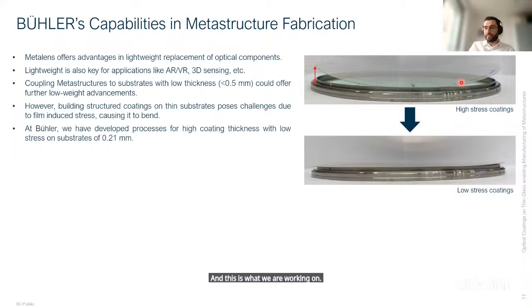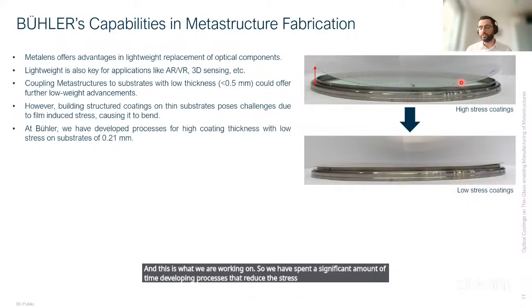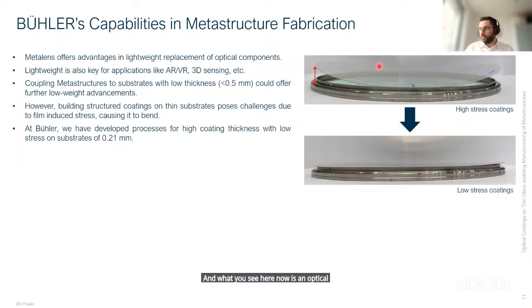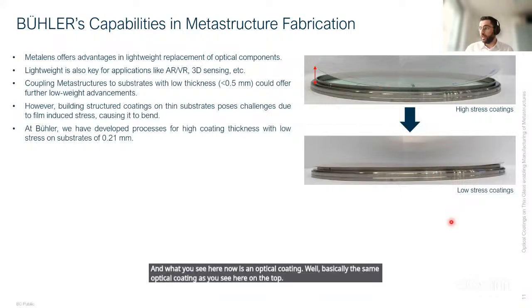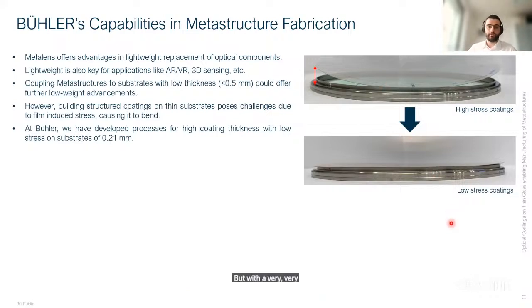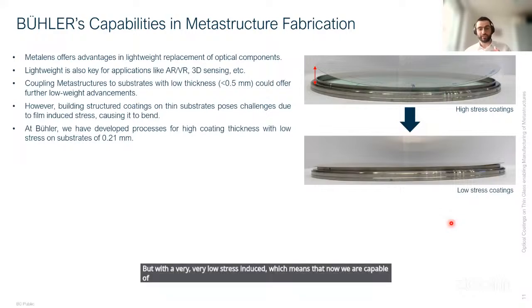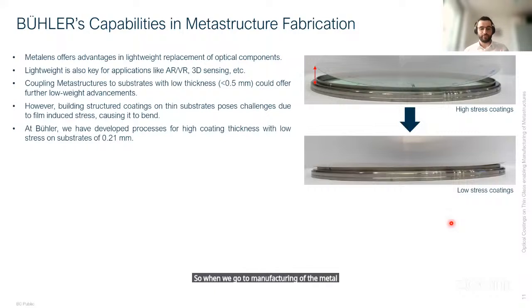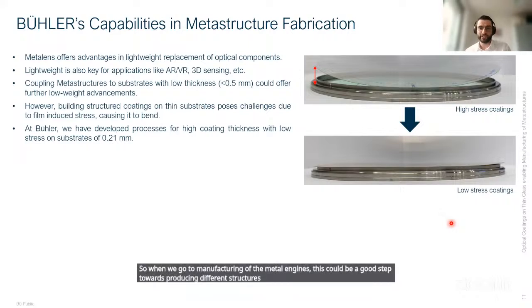So we have spent a significant amount of time developing processes that reduce the stress induced on the wafer. And what you see here now is an optical coating, basically the same optical coating as you see here on the top, but with a very, very low stress induced, which means that now we are capable of doing coatings with a certain thickness, which give rise to very little stress on the wafer, which means that they are bending less and less. So when we go to manufacturing of the metalenses, this could be a good step towards producing different structures and different types of coatings on wafers with a certain size.